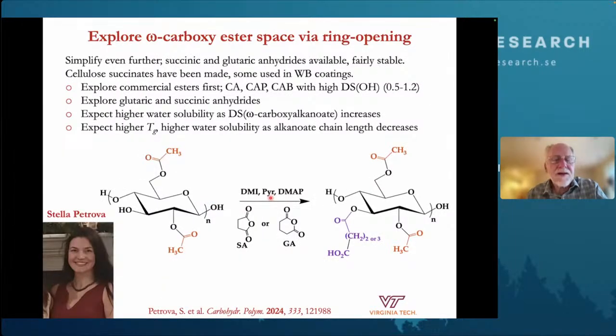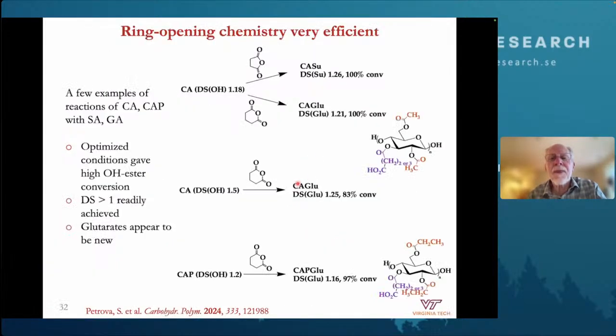And so the way we approach that, my student Stella Petrova, who's in a postdoc right now, she's recently graduated, approached the problem by a simple ring opening chemistry. Can we ring open succinic anhydride or glutaric anhydride with a cellulose ester starting material to make materials that, from our knowledge of structure property relationships, would have that right combination of hydrophobicity, hydrophilicity, and ability to prevent drug crystallization. And so that's what she embarked on. And she was able to develop conditions for this ring opening reaction that gave high conversions, that gave high degrees of substitution of the omega carboxy alkanoyl group, either succinate or glutarate, and gave her quite high yields.